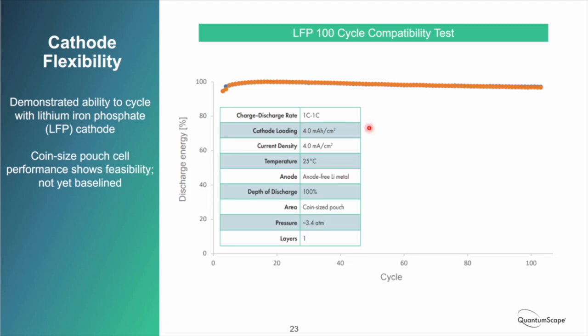So we made a 4 milliamp hour per square centimeter LFP cathode. That's a pretty thick LFP cathode. And just did a 100 cycle compatibility test of a few cells here. Again, these were small, single layer pouch cells where the active materials are roughly the size of a coin cell, but it's just to prove materials compatibility and show our customers, hey, if you want lower cost, lower energy density LFP, that technology works as well, and we can develop it.